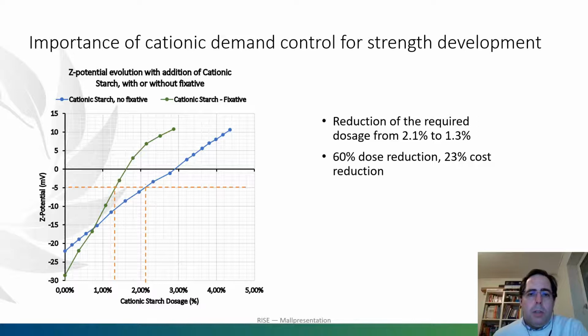What we could see is that to reach the same zeta potential, we can reduce the dose by about 60%. And even if we include the cost of the fixative, overall, it will be a 23% cost reduction. But if we look at this graph in another way, and we consider that normally the amount of starch that we can produce and that we can add in our machines is limited, it will mean that if we are not working with the cationic demand, we will not be able to reach a neutral enough zeta potential to really develop all the strength that the system can give.